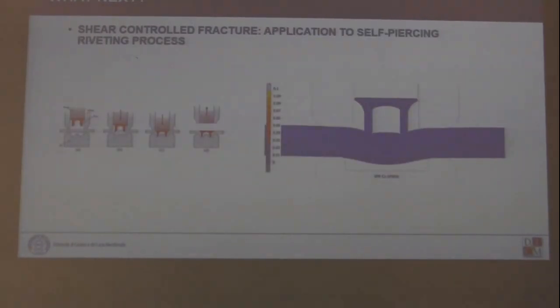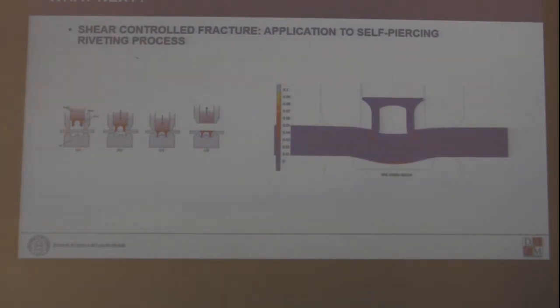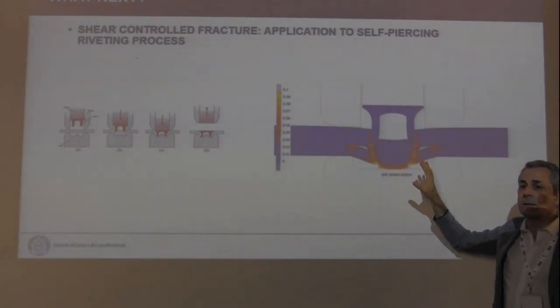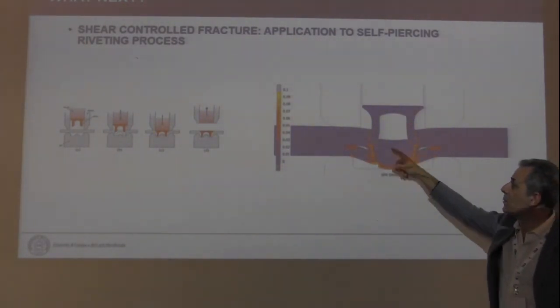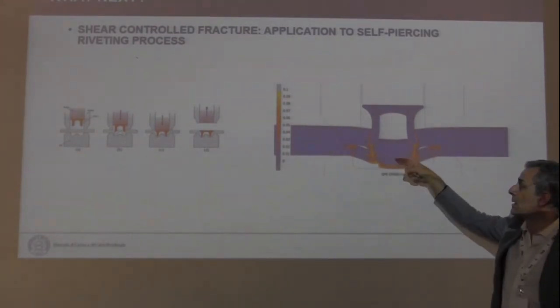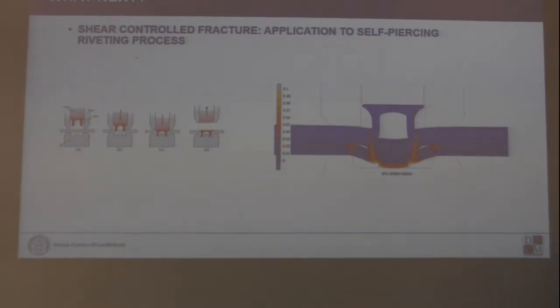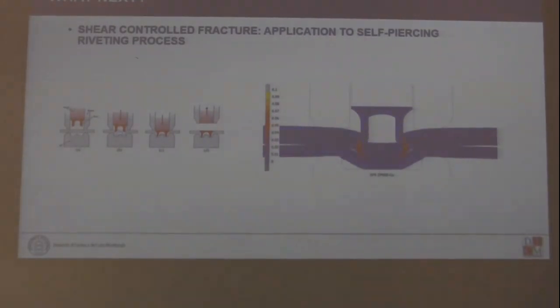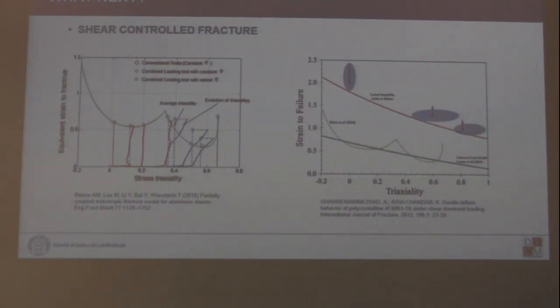With this method, we were able to predict, for instance, in the self-piercing riveting process, this kind of failure, which cannot be predicted with other more traditional damage models, in which you have a shear fracture occurring in both materials. This one is more brittle than the lower sheet. So there are some cases in which you will need this additional damage modeling for shear. But we are still discussing whether this is real, or also an artifact.